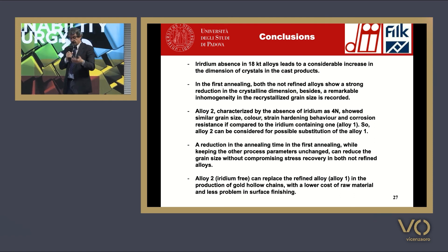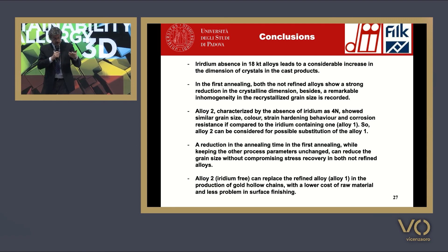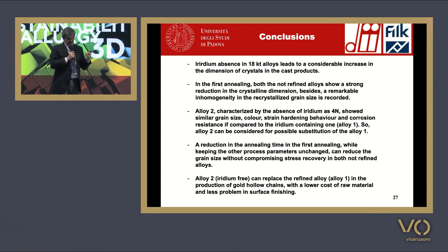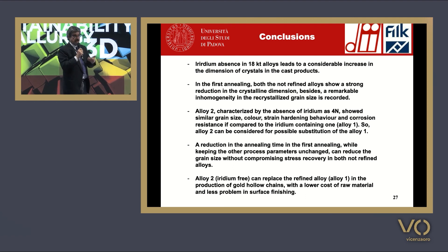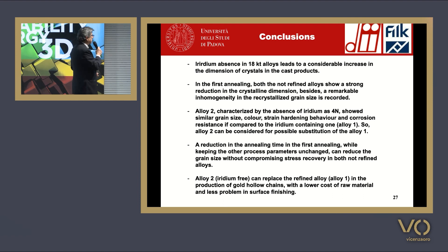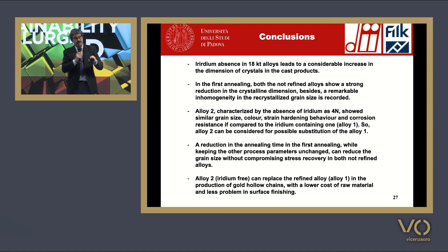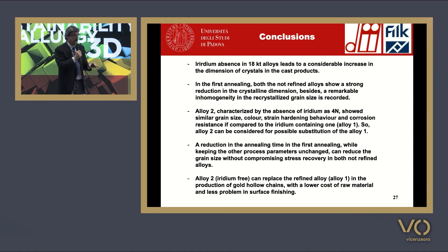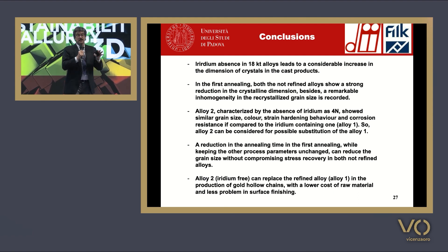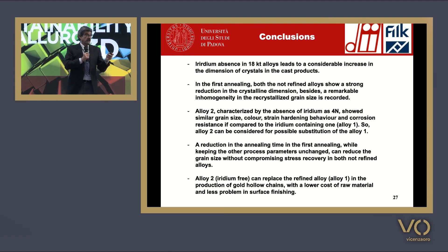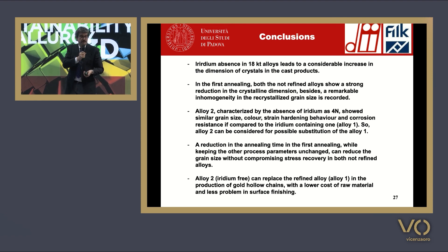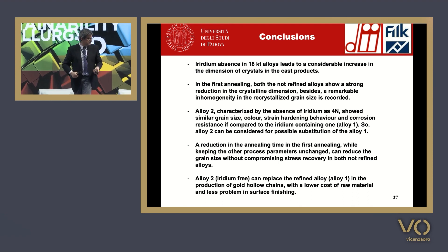The colors of the alloys are more or less the same. Using a colorimetric system based on the CIELAB system, when the color difference is lower than three, colors are not distinguishable by human eyes. So the refined alloy and Alloy 2 have a color that is more or less the same. We also studied the corrosion resistance, since we changed the composition, to verify if the corrosion resistance in artificial perspiration is the same — and in fact the result is more or less equivalent.